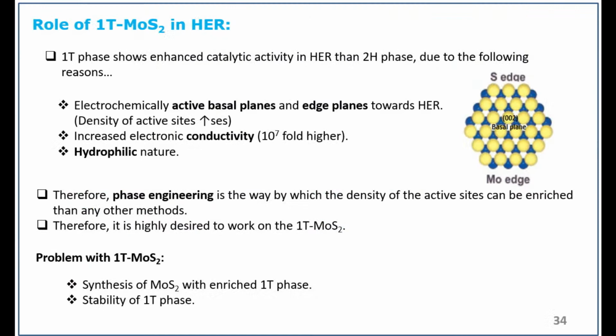So the 1T phase, how it's very important. The 1T phase shows enhanced catalytic activity in HER when compared to 2H. Electrochemically active basal planes and edge planes towards HER. The density of active sites increases because 1T has more density of active sites, and it increases the electronic conductivity 10⁷ fold higher than the 2H phase. That's very important. So this 1 crore times improved conductivity alone has its own dominance over the activity. And then it is hydrophilic in nature. Hydrophilic means water loving, so the electrolyte will penetrate easily throughout the MoS2 layer so that you have more active centers. Therefore phase engineering is a way by which the density of active sites can be enriched, and therefore it is highly desired to work on 1T MoS2.